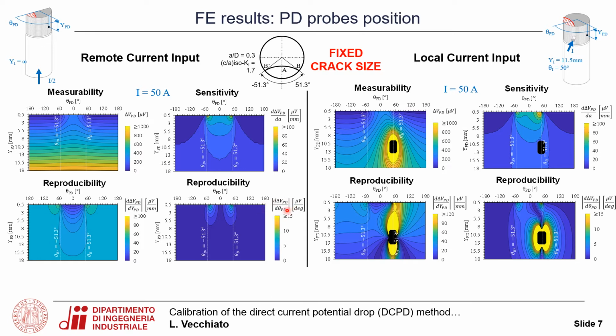In general, the sensitivity is higher whenever the potential drop probes are located as close as possible to the crack plane, so y_PD is as low as possible, and whenever the angular position is within the cracked surface, so between plus or minus theta_B. For the same region, the reproducibility also assumes the highest value. In general, it was possible to observe that the potential drop probes should be located as close as possible to the crack plane. In terms of angular position, that is a matter of choice.